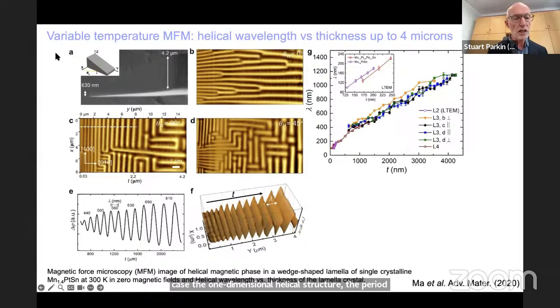And you can see here very nicely, if you look at C, this is a magnetic force microscopy image again of the out-of-plane components now. And you see the out-of-plane component is rotating from an up to a down direction. This is shown in a line through this image in E, and you can see very clearly the magnetization is rotating from up to down with a period that is increasing substantially as the thickness of the wedge is increased from the left to the right.